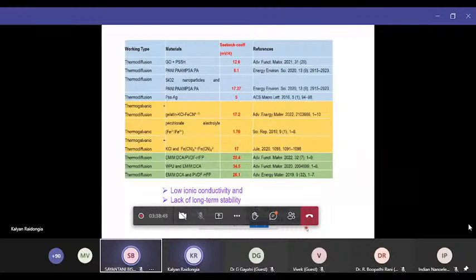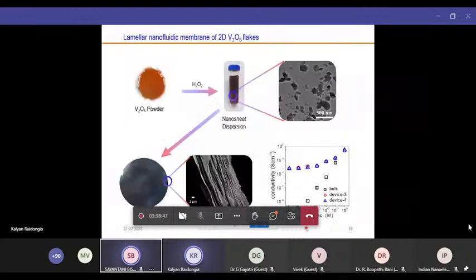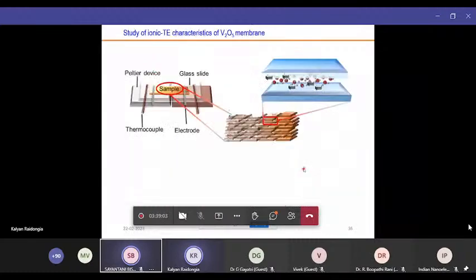So again, here we tried to explore nanofluidic systems prepared with vanadium pentoxide nanosheets, because vanadium pentoxide is an inorganic material. It's an oxide. It can sustain very high temperature, and it also displayed a very high ionic conductivity, almost as good as Nafion. So we believed this to be a good system. We made a membrane and connected a simple device with two copper wires attached through silver paste, and placed it under a temperature gradient using a Peltier device. Then you can see that ions can move from one side to the other.